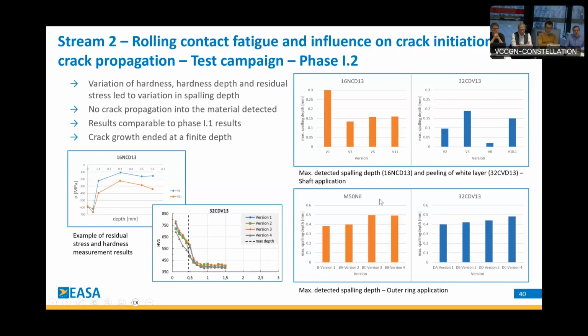In phase 1-2, we had a variation of hardness, the hardness depth, residual stress, and so on. And we saw a variation in spalling depth. We also did not notice a crack propagation into the material here. And the results are generally comparable to the phase 1-1 results, which means a crack growth ends at a finite depth, mainly in line with the spalling depth. Just an example here on the left side of the residual stress and the hardness measurement results that was done, also to verify that the manufacturing settings, the desired targets that we want to have, are met.